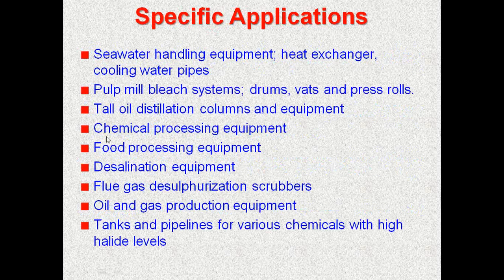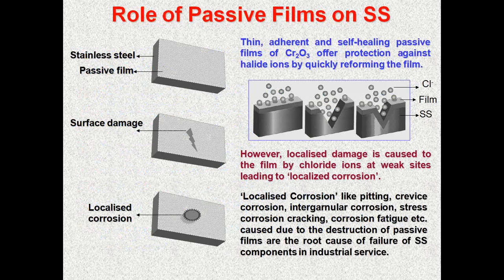You can see I have also put the typical applications, including flue gas desulfurization, oil and gas production, and various chemicals at very high halide levels, food processing, solvent distillation columns, pulp and paper bleach, and seawater handling. Now we have seen all this, austenitic, duplex, and superaustenitic. One important factor is that, as I told, why this stainless behavior? Because of the chromium oxide film that is present whenever the chromium content is beyond 10.5% in the steel. And that is how we get this thin adherent self-healing chromium oxide film, which provides the protection, but they are attacked by halide ions.